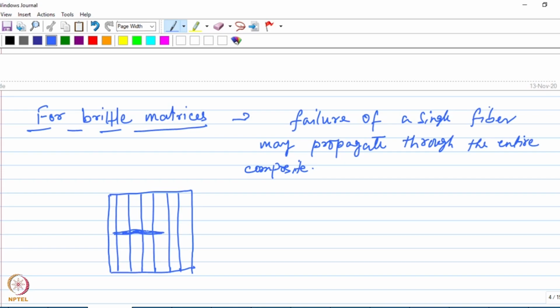And as I said, the catastrophic propagation of the crack can only be prevented if some relaxation is developed at the crack tip, right? So only when the stresses can be relaxed, this kind of catastrophic propagation of the crack can be prevented. And in this case, when the matrix is brittle, that relaxation can only be developed through the interface if it is weak, if the bonding at the interface is weak. So this will relax the fibers and prevent the catastrophic crack growth.